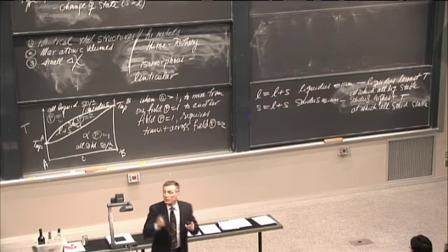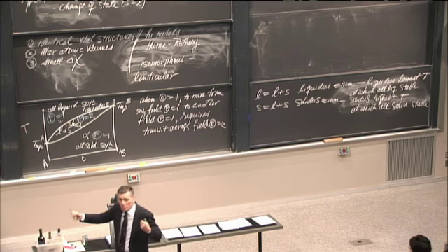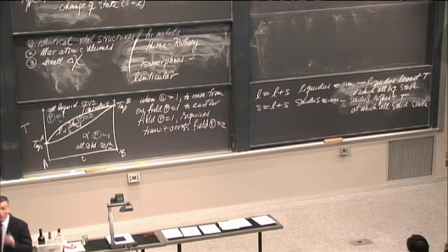Here's a ceramic system. This is nickel oxide, magnesium oxide. It's not metals, but they have identical crystal structures, very similar atomic volumes. They're ions, so we have nickel and magnesium substituting for one another on the cationic sublattice. So they must have very nearly equal sizes. If I see a lenticular diagram, it means they must have similar atomic volumes, which means the dominant defect in here must be Schottky, not Frenkel, because Frenkel needs a big difference in atomic volume. If you had a big difference in atomic volume, you wouldn't have had a lenticular phase diagram.